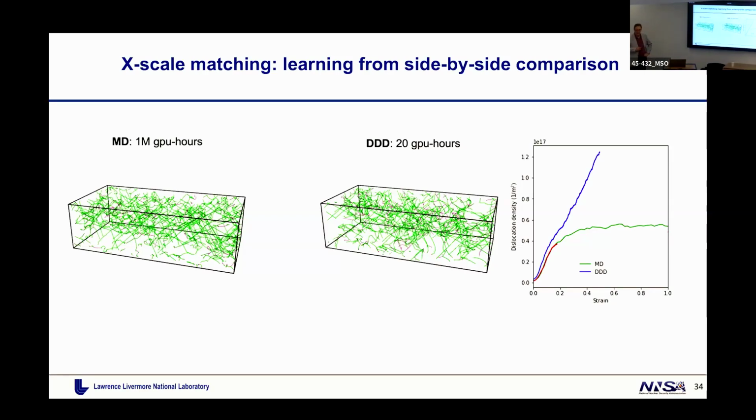However, we also found another interesting aspect of why you want to do both. This is what these particular simulations reproduce in terms of dislocation density. This is MD, green, and the blue is DD, and they're very different. Whereas in MD, dislocation density reaches a stationary state, as I was previously describing, it never happens in DD for some reason. Dislocation density keeps increasing.